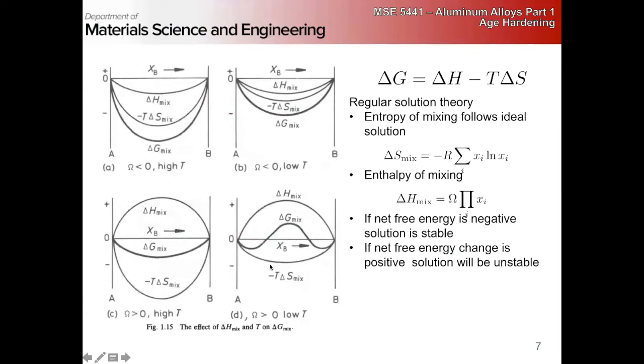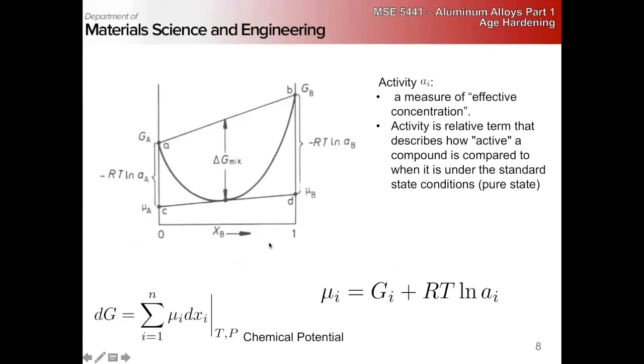But what happens if we lower the temperature, right? Our entropy term becomes less negative. Our enthalpy term is still positive, so we can end up with a delta G of mixing where the enthalpy term dominates and we become positive, in which case this mixture will phase separate.